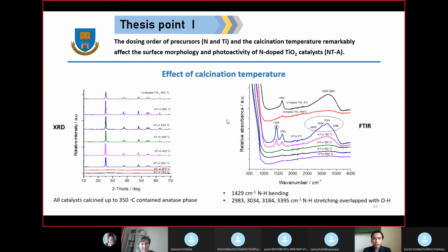To study the effect of the calcination temperature, we calcined the catalyst at different temperatures. From the XRD result, we see that up to 350 degrees, the catalyst consisted of the anatase phase, but with different crystallite sizes. The FTIR spectra show a typical peak after nitrogen modification in two areas.